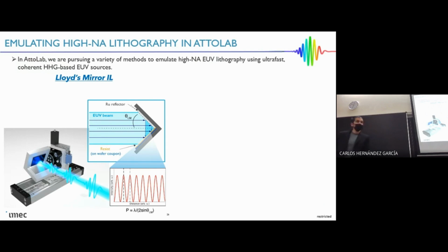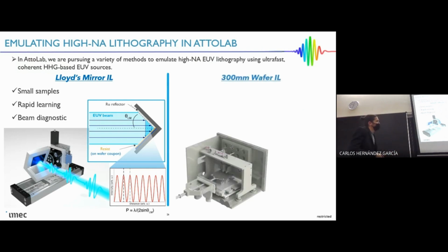So it's quite a simple interference phenomenon with a pitch, or a wavelength of this grating, that's equal to the wavelength of the light divided by the sine of this angle. So from this, we can actually print very small features, something like 20, 30 nanometers with a relatively simple device. And we like this one because it's a good test device. It has small samples. It's very quick. And it allows us to diagnose things, see if we have the flux and the stability in our beam to be able to actually even do this.